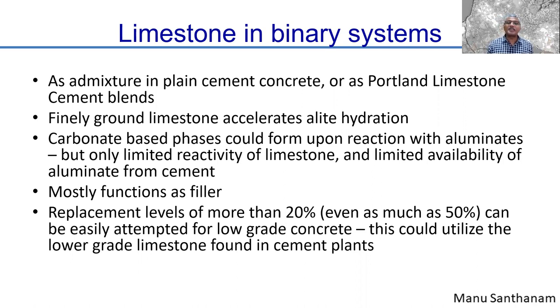What do you mean by good quality, low-grade concrete? I mean where strength development is not that critical and where the durability levels that you require in coastal environments, you don't really need those. So for instance, when you're making blocks or bricks with concrete, why do you need such high levels of durability with blocks or bricks? You need durability in concrete because you want to protect the reinforcing steel. But in plain concrete, you don't really have to worry too much about that. Of course, you need to worry about efflorescence, water absorption, and things like that. But those have to be properly designed against.